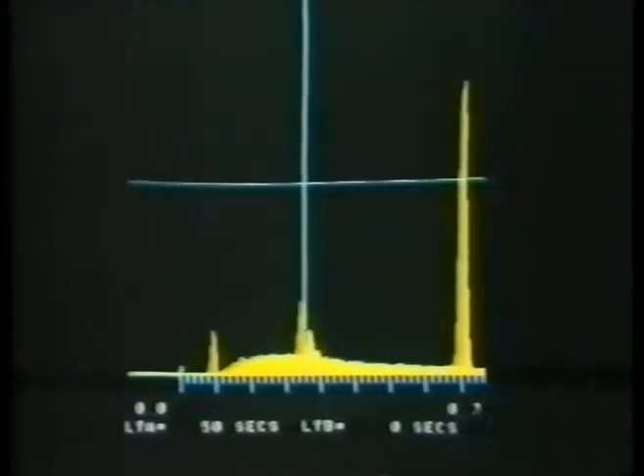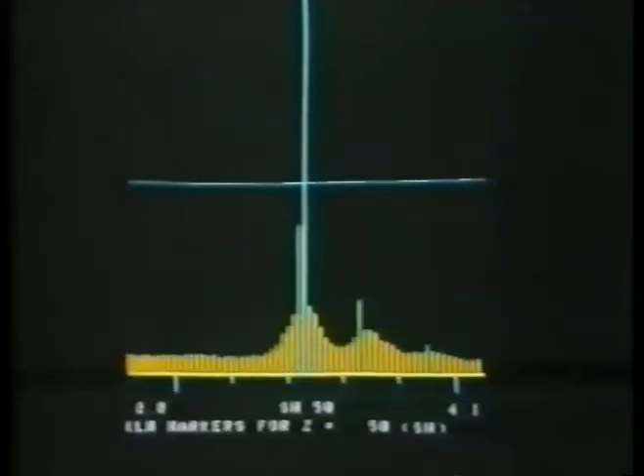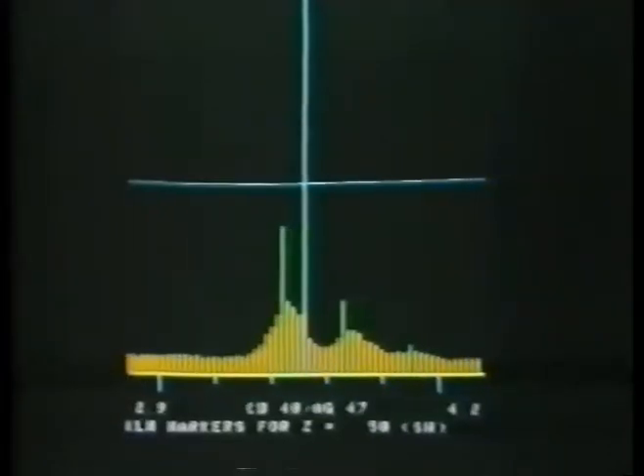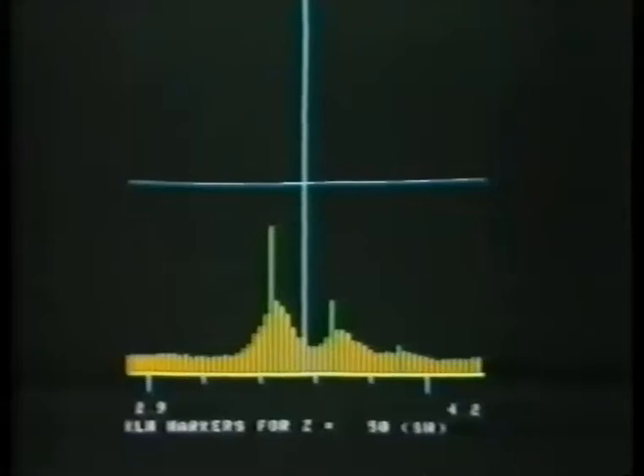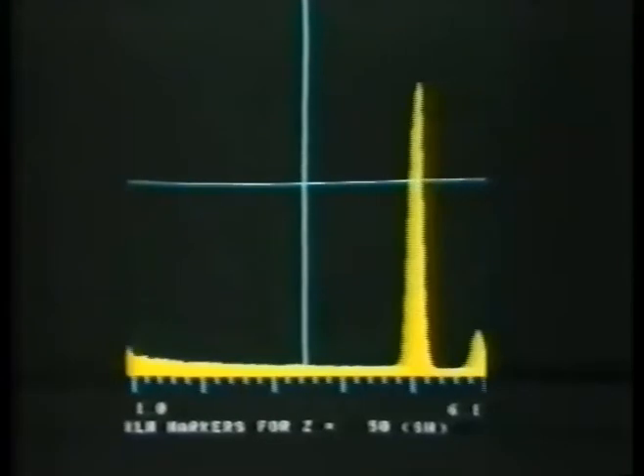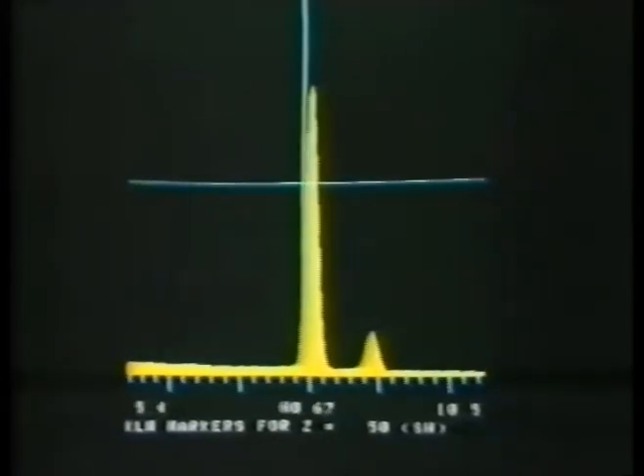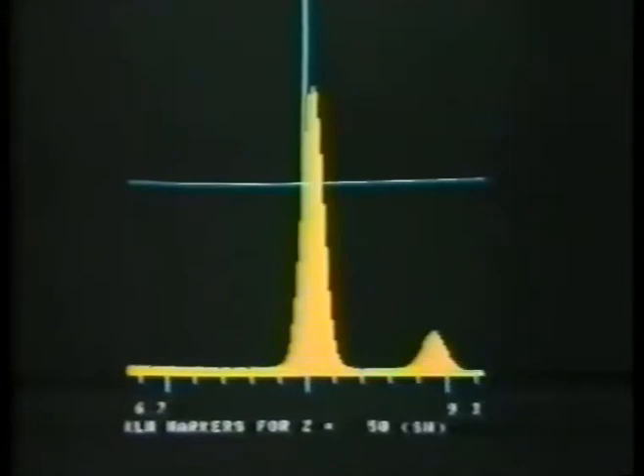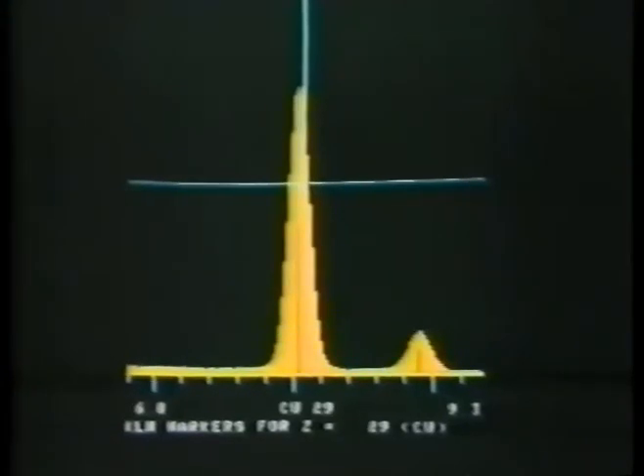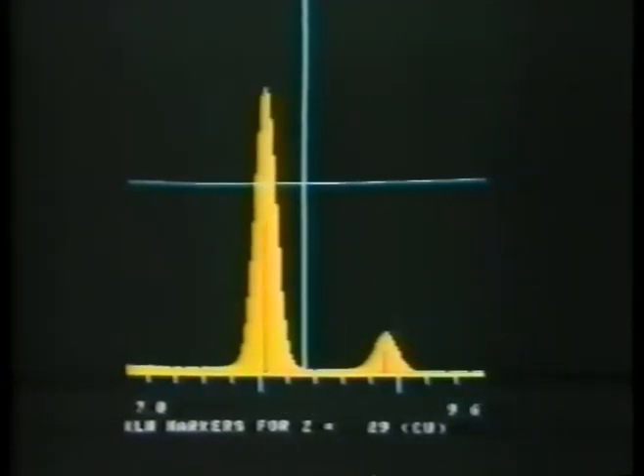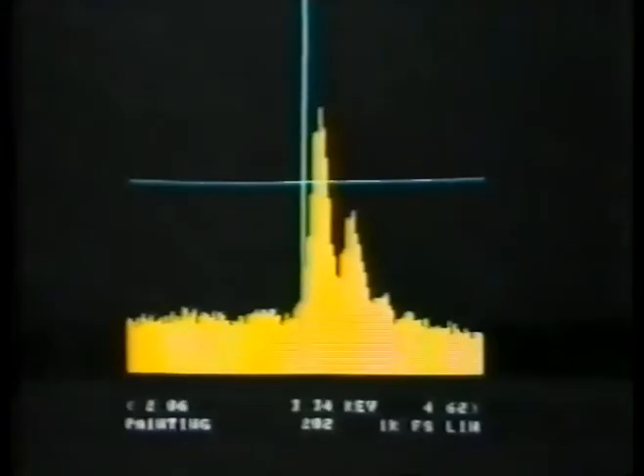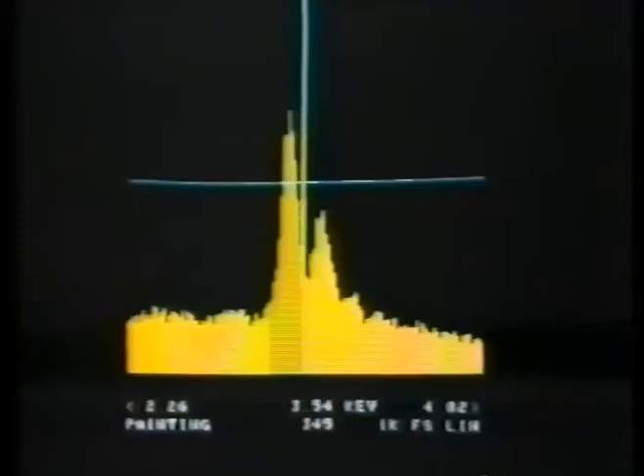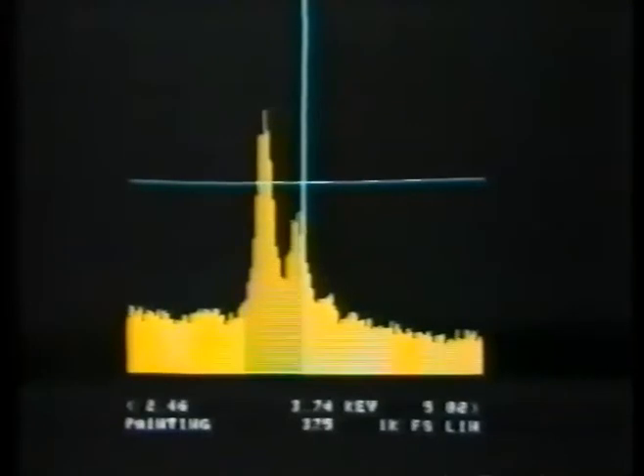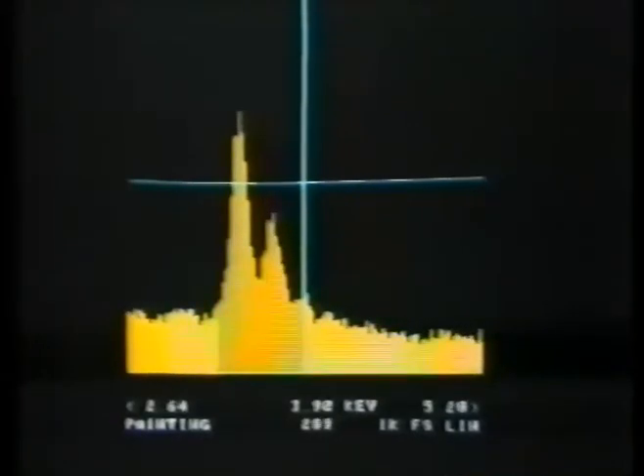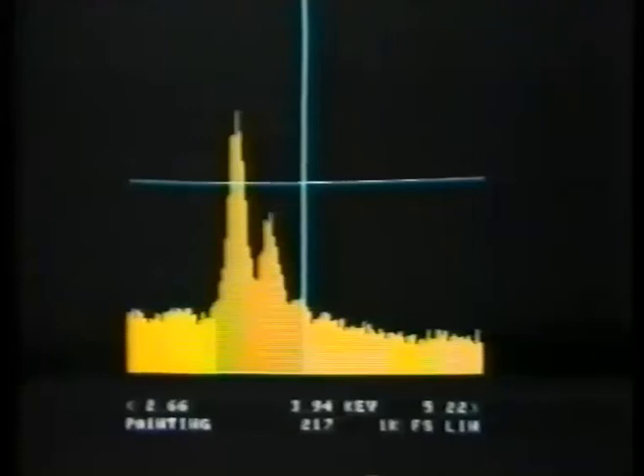These peaks suggest that tin is present. The green standard marker lines for tin, which are stored in the machine, confirm these peaks to be tin. Another set of reference markers confirm that these peaks are copper. This is just an overall analysis which doesn't tell us any more than the chemical composition. But we can also ask the machine to scan the same area, but this time looking at how just one particular element is distributed within the area.